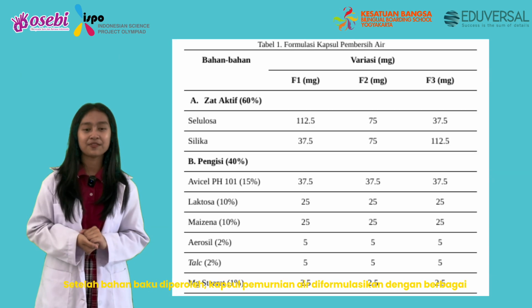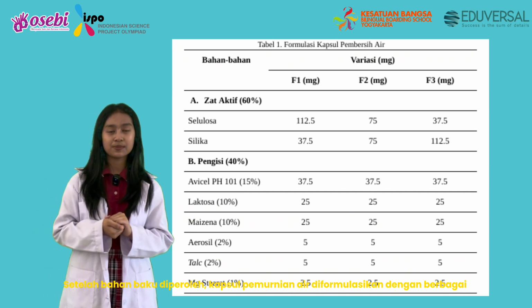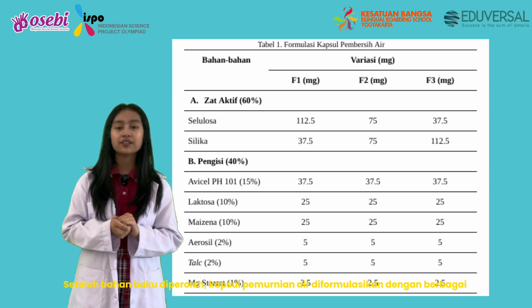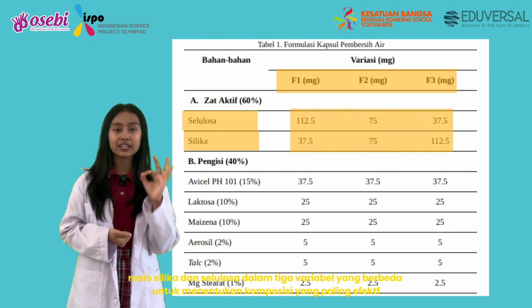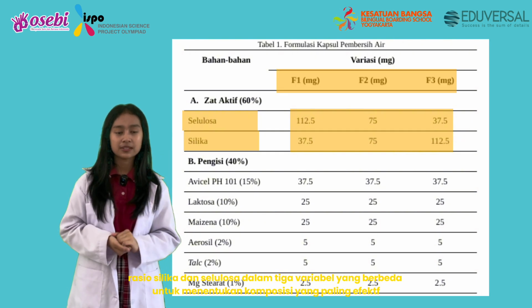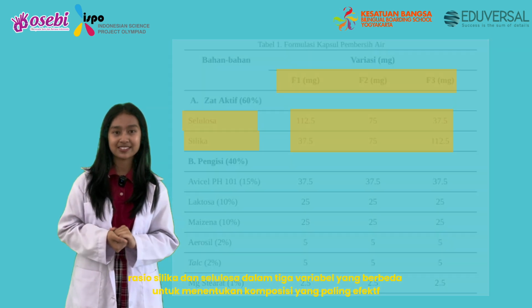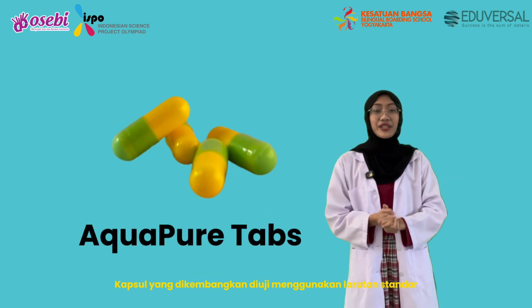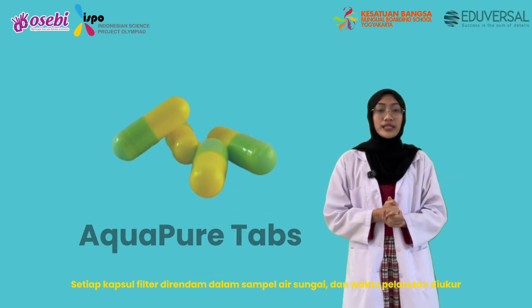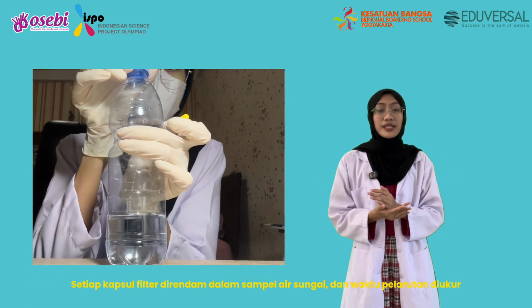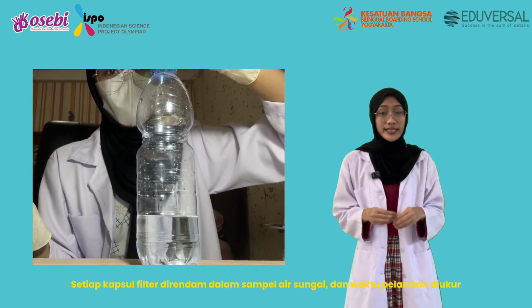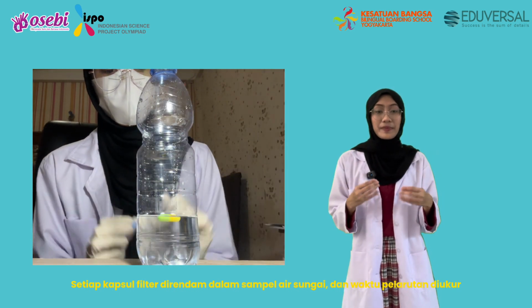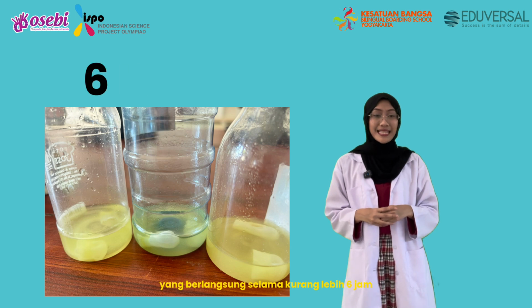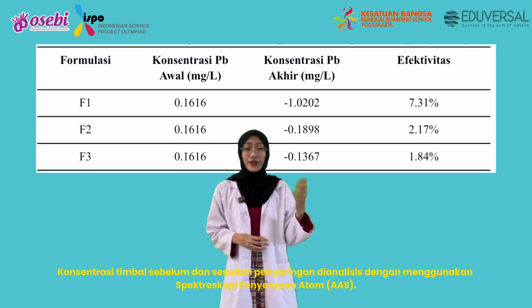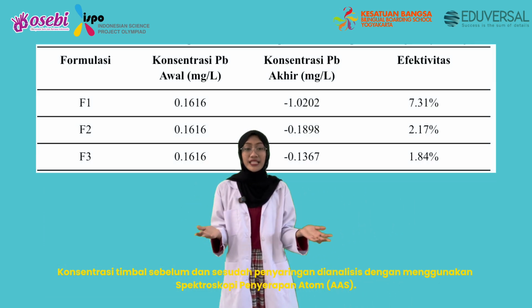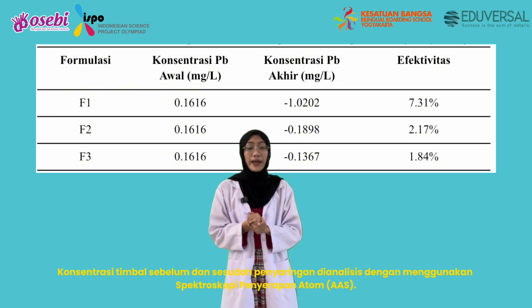Once the raw material has been obtained, the water purification capsule is formulated with varying ratios of silica and cellulose in 3 different variables to determine the most effective compositions. The developed capsules are tested using a standard solution testing procedure. Involved, each filter capsule is immersed in the river water sample, and the dissolution time is measured, lasting for approximately 6 hours. The lead concentration before and after filtration is analyzed using atomic absorption spectroscopy.